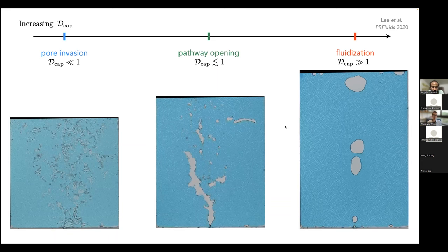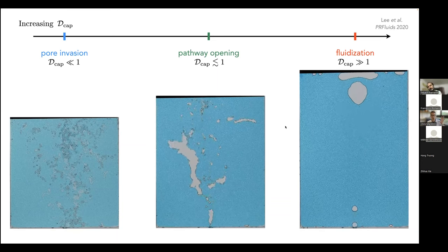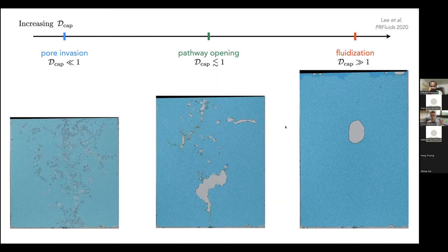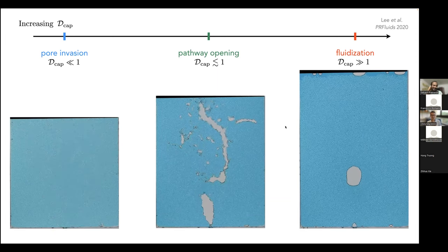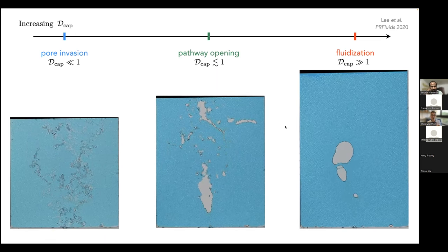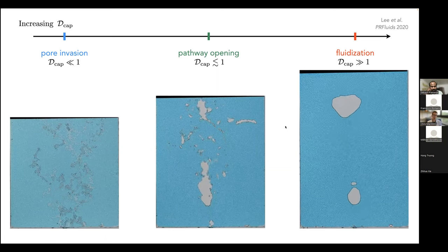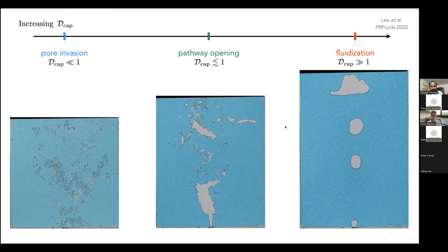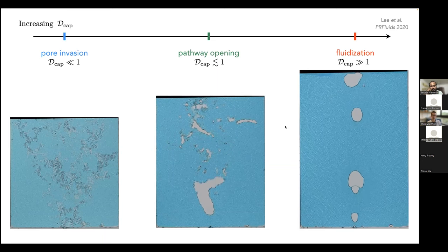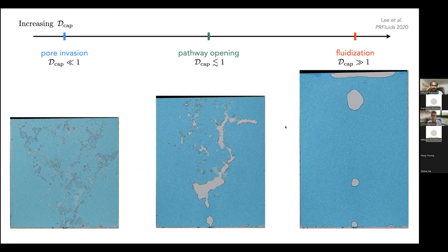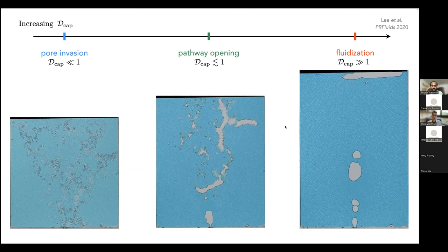Yeah, no, I completely agree. I think the stress strain curve that I showed for the sponge at the beginning, as I mentioned, is not the simplest stress strain curve in the world. It's not just linear elasticity, but it's a lot simpler than what you see in these videos, right? It's a system that just deforms in a purely reversible way, purely elastically. And as long as you have the strain energy function that corresponds to that problem, it's actually not that hard to build into this system. I think this material is much more complicated rheologically than that material. That would be the main challenge if we wanted to extend our model to this particular set of experiments: it would really be about the rheology of the solid. I think the fluid stuff is more or less taken care of at this point.